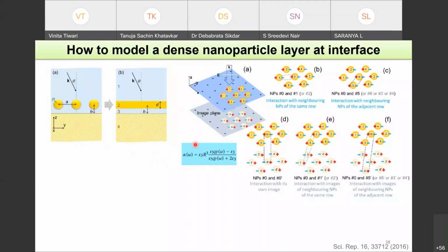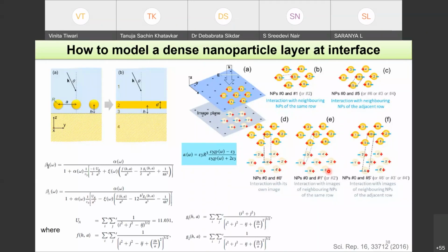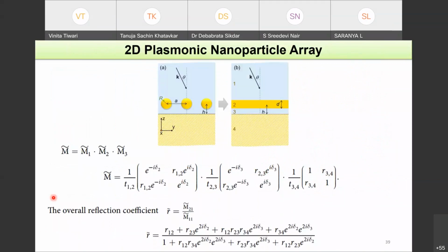So this is an illustration of different coupling. Let us take the center nanoparticle. It is getting coupled from the nanoparticles on the sides, from its own image, from the image of the neighbors and of the same row or adjacent rows. And when you compute all these interactions together, you will be able to find out what is beta parallel and beta perpendicular. So these are the effective polarizabilities of the nanoparticles in each of these layers. And once you know that, you can obtain what will be the epsilon parallel and epsilon perpendicular for this layer.